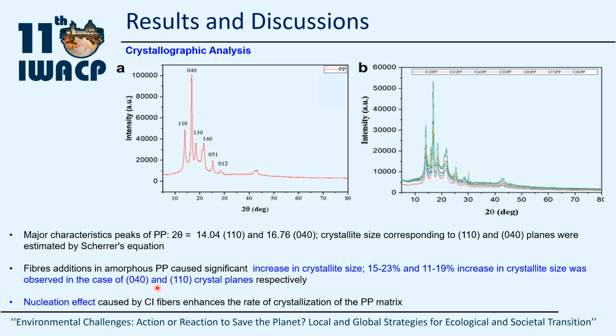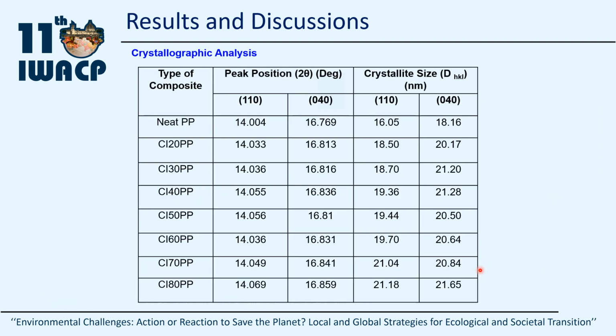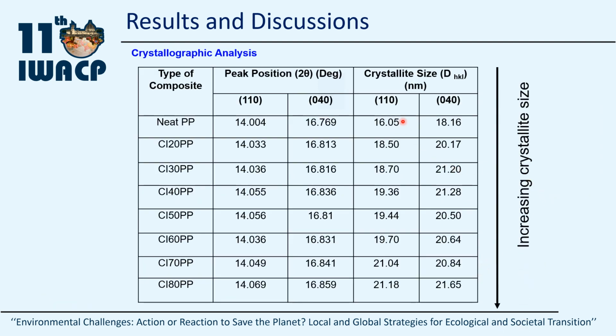In case of the 040 crystal plane, it ranged from 15 to 23%, whereas in case of the 110 crystal plane, it ranged from 11 to 19%. And the similar can be observed here. In case of the 110 plane, it ranged from 16 to 21.18, whereas in case of the 040 crystal plane, it ranged from 18.16 to 21.65. It is worth mentioning here that the increase in crystallinity of the PP matrix will have a significant impact in improving the thermal stability of the polypropylene matrix, and the similar we have seen in case of thermal stability while we were discussing it.